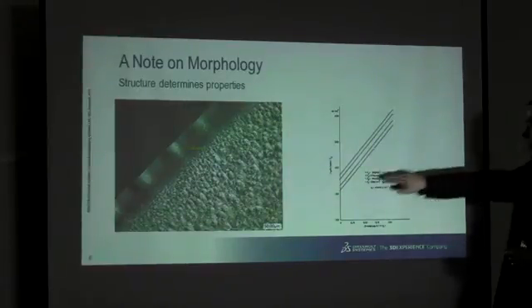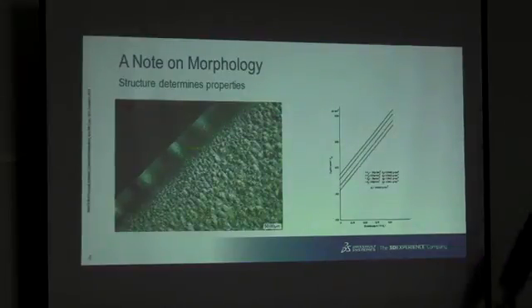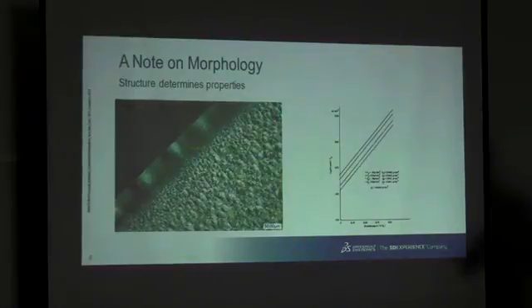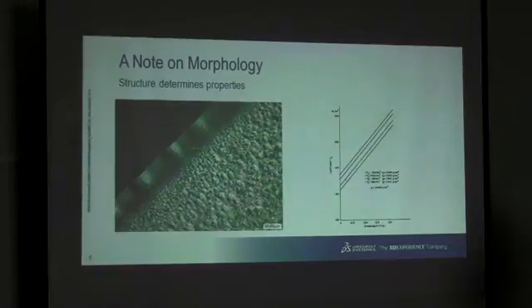And what you can see is that you can increase the ultimate tensile strength by simply stretching the fibers. Well, obviously, that's how it works. And that also leads you, unfortunately, to draw conclusions that, well, all I need to do is stretch my fibers long enough and then I can reach infinite amounts of UTS. But of course you can't. Theoretically, on a micromechanical level, you can reach some ridiculous theoretical Young's moduli of, I think, close to 300 gigapascals for polyamide. But of course that doesn't happen because those conditions don't exist.